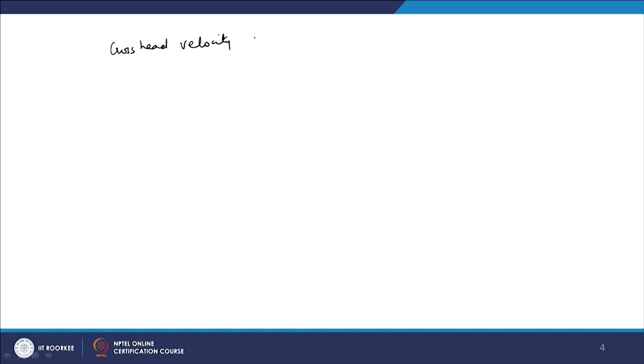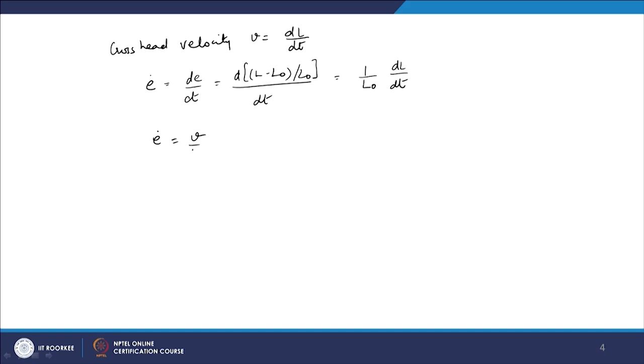So, basically crosshead velocity, if I want to find out, V will be equal to dL upon dt. That is the movement of the crosshead divided by the time it takes for that movement. So, in terms of simple engineering strain rate, e dot will be equal to de upon dt, that will be equal to d of (L minus L naught) divided by L naught, upon dt. This is all in differential form, since L naught is a constant, it comes out as 1 upon L naught and this becomes dL by dt. So, my e dot becomes V upon L naught.